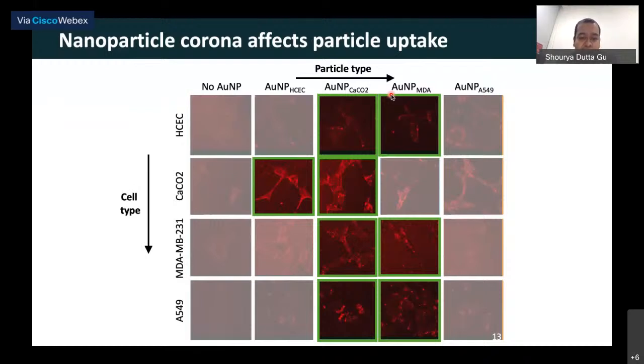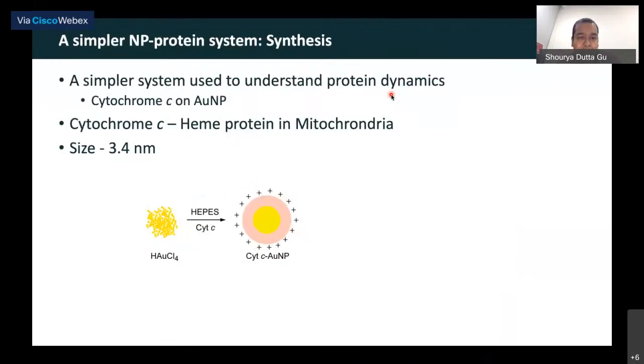So what that is telling us is the type of nanoparticle matters significantly. And that is precisely why we want to understand how this protein corona affects, right? But that is very complicated. So as an easier system to study, what we did was we synthesized particles with a known protein corona, right? In this case, we are using this molecule called cytochrome C. This is a molecule that is commonly found in the mitochondria of all organisms, including humans. Now, this protein has a size of around 3.4 nanometers, right? And this is positively charged at neutral pH.